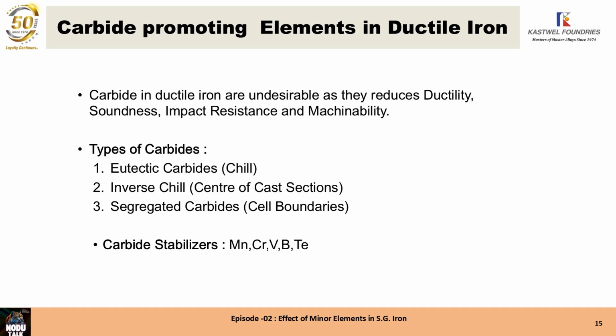Last time, when I was speaking about the composition, I had mentioned to you that in all heavy section SG iron, the manganese level should be as low as 0.3% and not to exceed 0.3%. Because in liquid metal, if the manganese is 0.3%, in heavy section SG iron castings, in the center of the section, the manganese segregation takes place up to 10 times that value. If it is 0.3% in the liquid metal, 10 multiplied by 0.3 is equal to 3%.